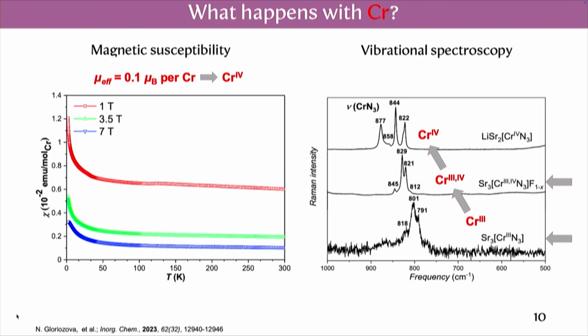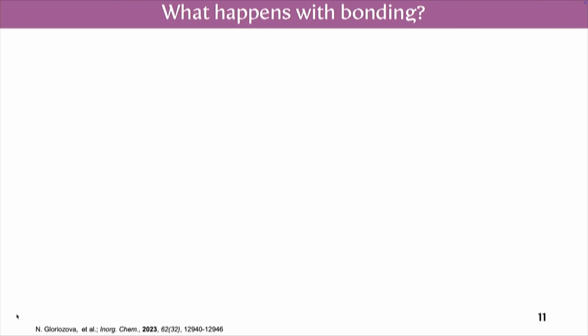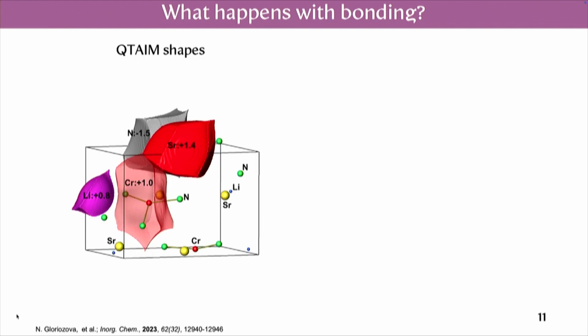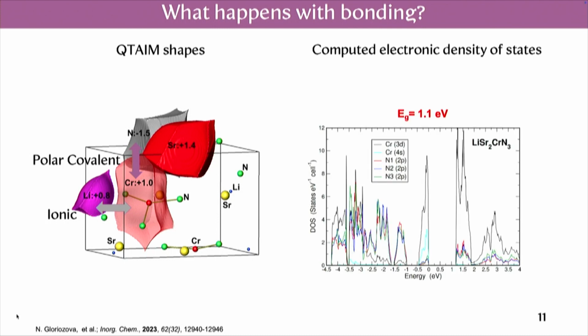Okay, what else do we need to know to use these materials as batteries? We need to know the bonding in the compound. For that, we performed some calculations, and from the QTAIM shapes of basins, we established the bonding inside the compound. The interface between chromium and nitrogen is planar, which leads to covalent polar bonding, whereas the interface between lithium and nitrogen is more round, which leads to mostly ionic bonding. Moreover, we checked the conductivity of the compound, which shows semiconducting behavior with a small band gap of 1.1 electron volts.